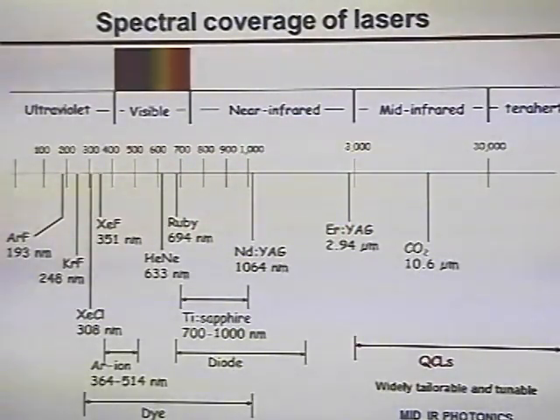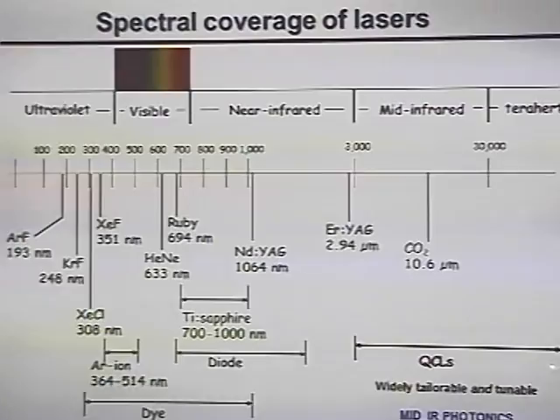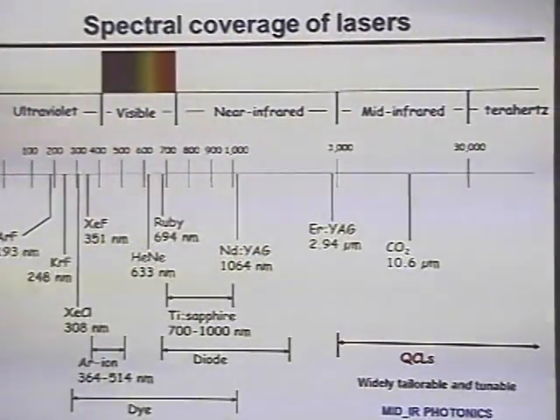What the quantum cascades have done is two features using the same combination of material. This is very significant. Just by varying the layer thickness, you can cover the whole wavelength range from 3 to roughly 25 micron wavelengths. In principle, you can go with the same material to 300 micron, but for practical reasons, if you want to cover from 30 beyond to 300 micron, it starts bordering the field of electronics. Then you switch to gallium arsenide alloys with the same principle. You just vary the layer thickness. You can change the wavelengths practically continuously up to 300 micron or actually beyond. So this is tailorability.